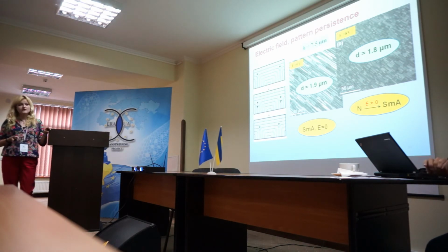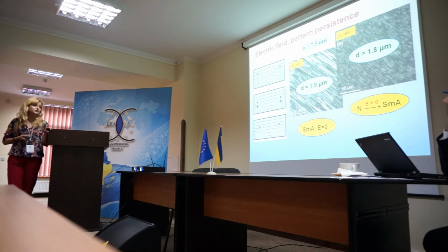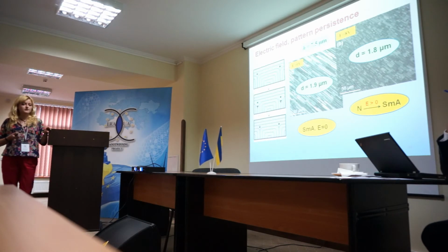It requires formation of new dislocations and moving all defects, which requires a lot of energy. And it seems to be too expensive in energy terms, so that we are not able to change either periodicity or thickness while varying the electric field in the smectic phase.